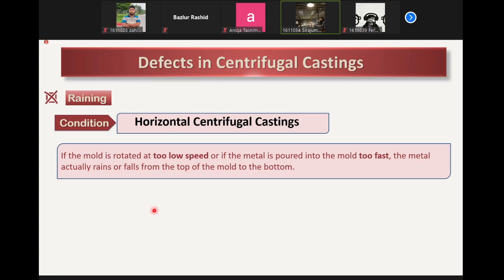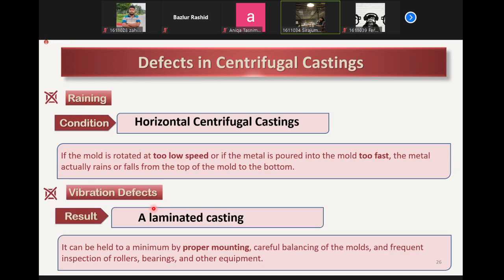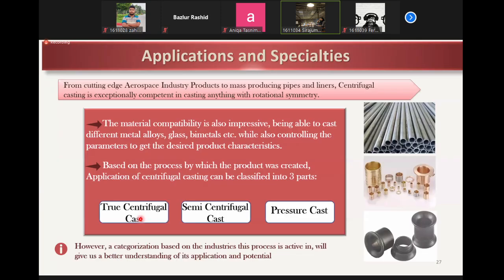Raining is a phenomenon that occurs in horizontal centrifugal castings. If the mold is rotated at too low a speed or if the metal is poured into the mold too fast, then the metal actually rains or falls from the top of the mold to the bottom. Proper process control can eliminate raining. Then the vibrational defect. Vibration can cause a laminated casting. It can be held to a minimum by proper mounting, careful balancing of the molds, and frequent inspection of rollers, bearings, and other equipment.